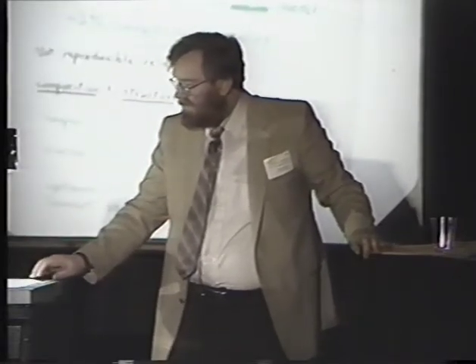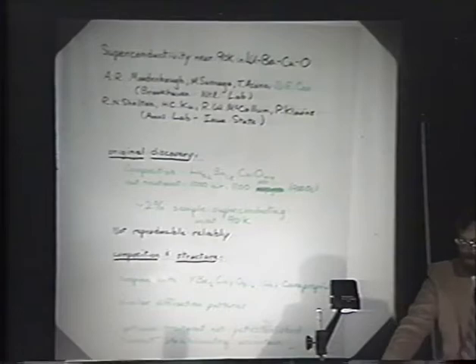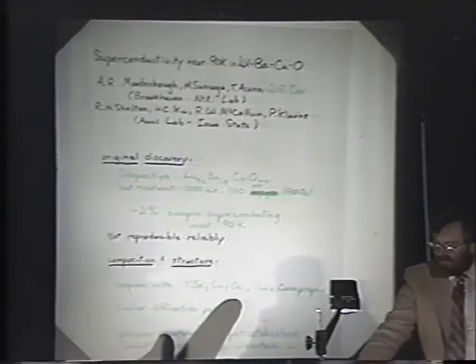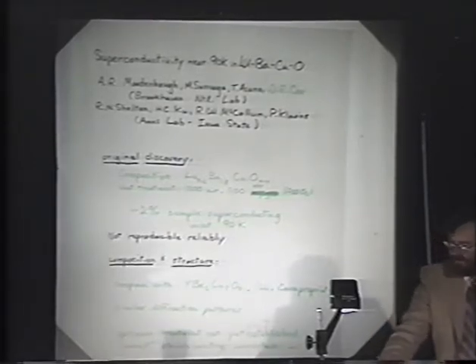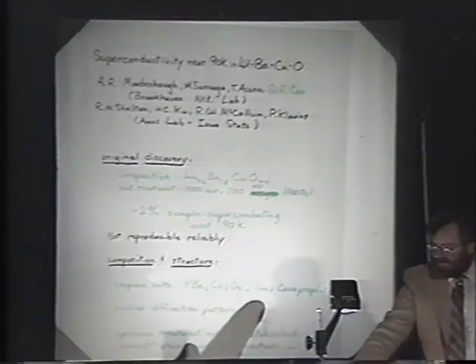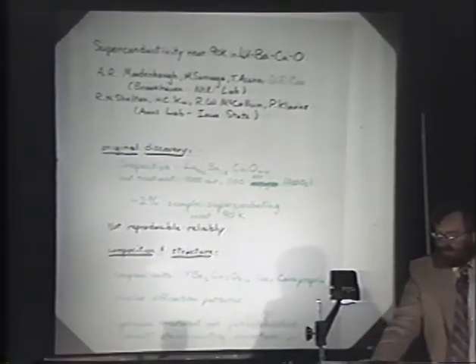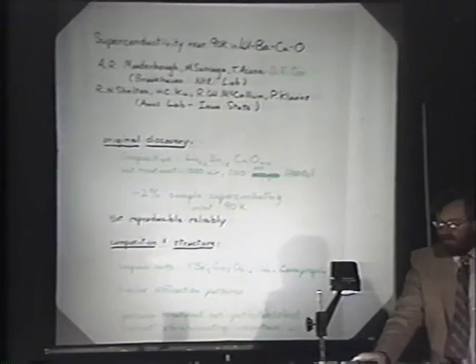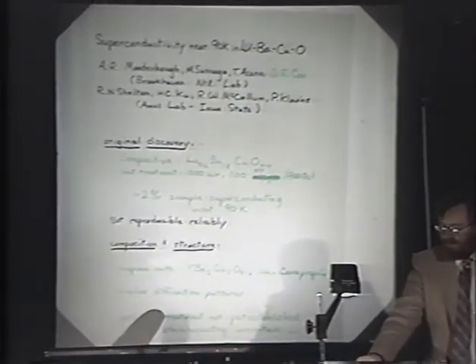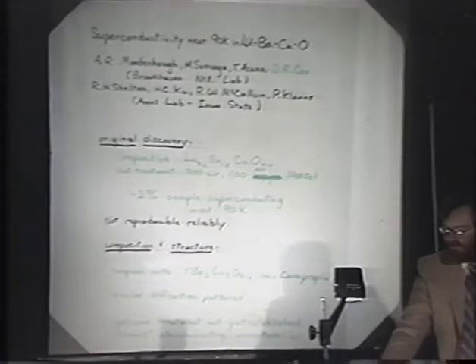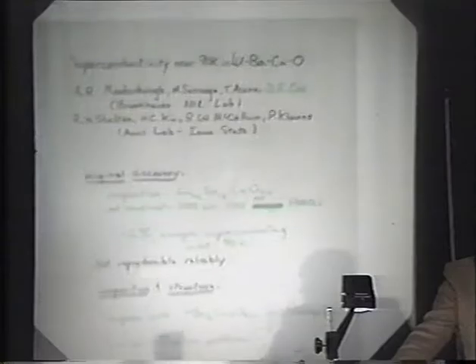And we want to make sure you know that we're in the high TC business, so I'll show you this slide. We're making what we think should be yttrium, barium-2, copper-3, oxygen, something, following Wu and Chu's preprint from AT&T Bell Labs. The X-ray diffraction patterns of our multi-phase sample show similar diffraction patterns, but the optimum heat treatment hasn't yet been established. Okay, John?